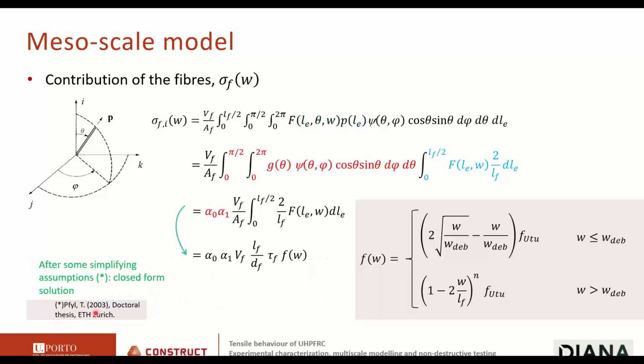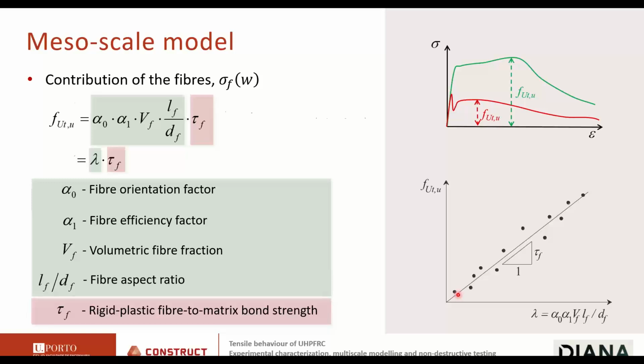Then after the work of Thomas Pfyl in Zurich, he developed a very clever closed form solution for this integral, which requires some simplifying assumptions: you have a function of the crack width that varies between 0 and 1, and then a constant value over here, which is basically the post-cracking tensile strength of the material. Here you have the equation for this function for the debonding or fiber activation stage, and here for the pull-out stage. Here we have this value, the fiber post-cracking strength, or the maximum value of the contribution of the fibers.